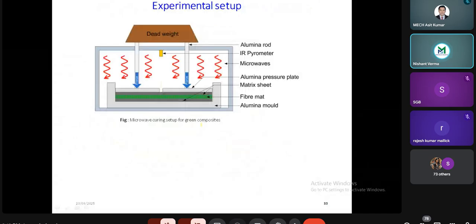So this is the experimental setup in the case of fiber reinforced composite. We place a sheet of polymer, and after that sheet, we can also place pellets. After that we place the fiber and again pellets. In this way we make the sandwich structure, and we have used a dead weight to generate force on the mold. This is the pressure plate.